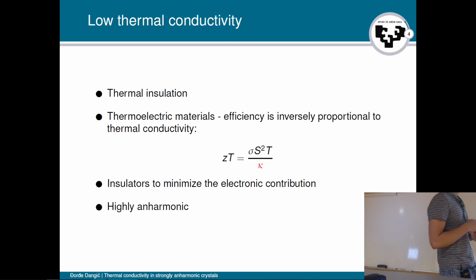Another reason why we want low lattice thermal conductivity is in thermoelectric materials. Thermoelectric materials are the ones that directly convert heat to electrical energy or vice versa, electrical energy into heat. And the efficiency of these materials is governed by the thermoelectric figure of merit, which we denote by ZT. And ZT can be calculated with this formula here. As you can see, the ZT or figure of merit is inversely proportional to the lattice thermal conductivity. So if we decrease the lattice thermal conductivity, we increase ZT and we increase the efficiency of thermoelectric materials.